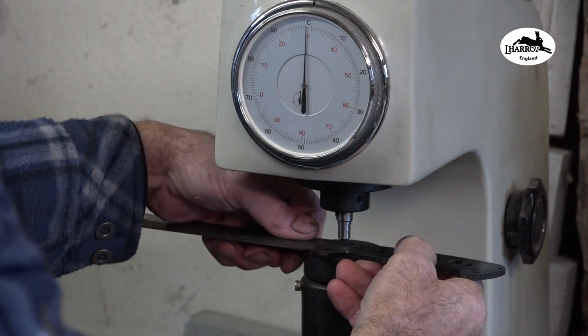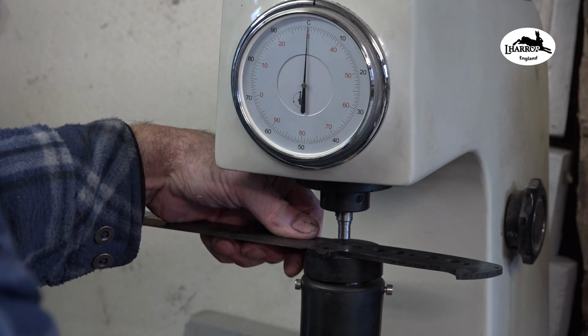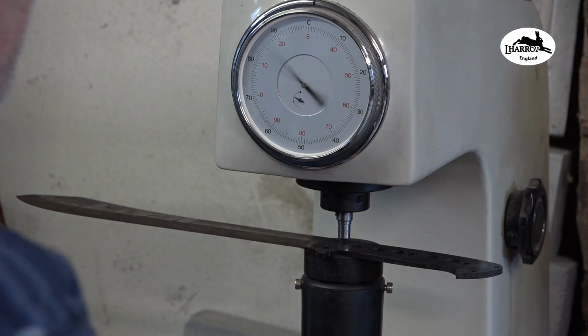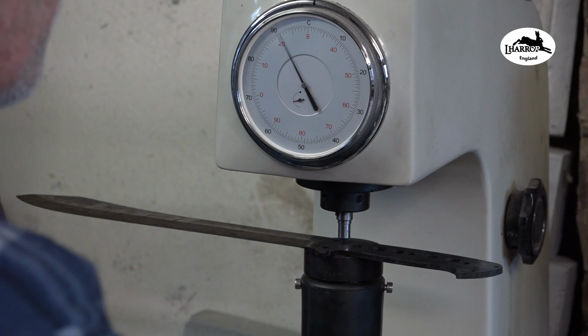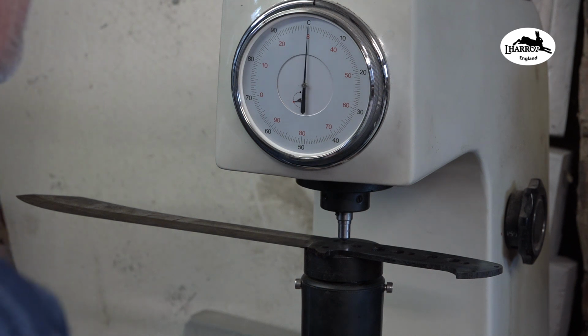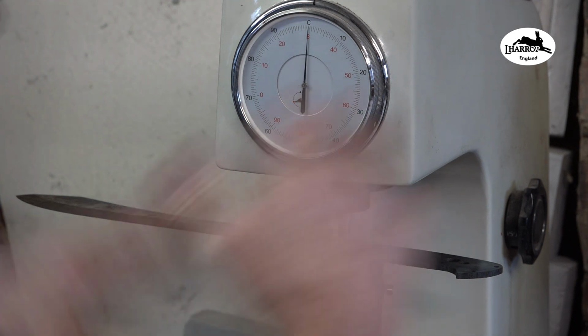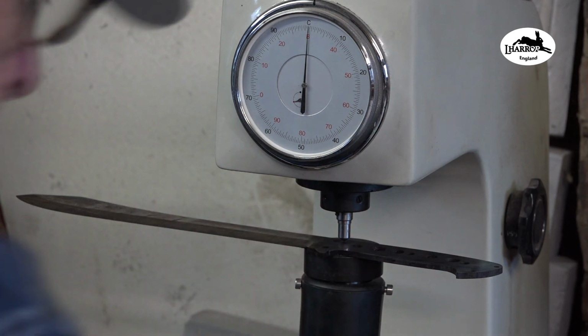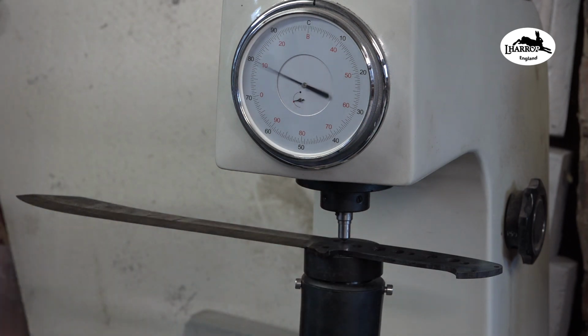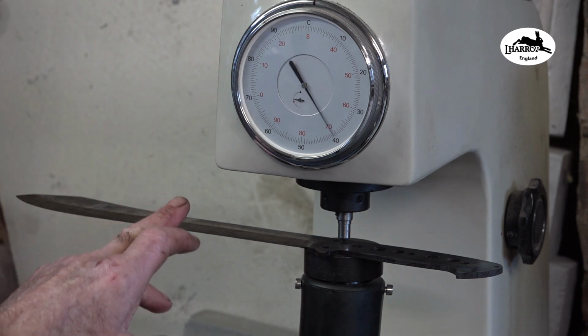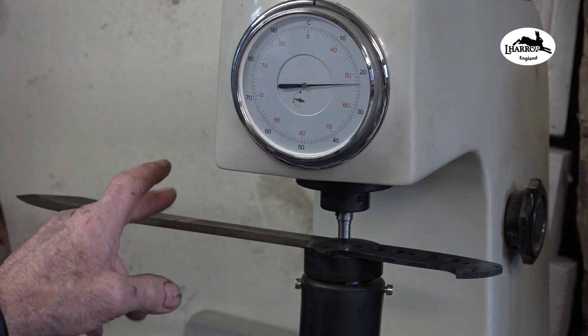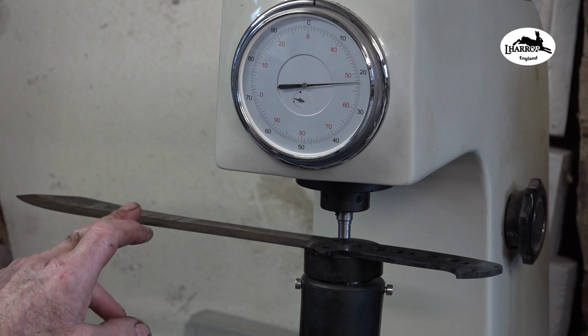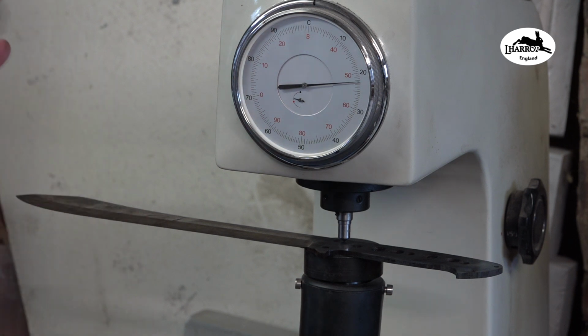Something I had to do, guys, because my core steel is at 63.5 HRC. The jacketed Damascus was at 64 HRC. If I temper this blade down to reduce the hardness of the Damascus, I will ruin the toughness of my core steel. It's just one of those things.